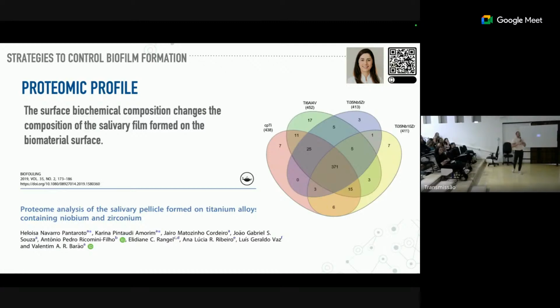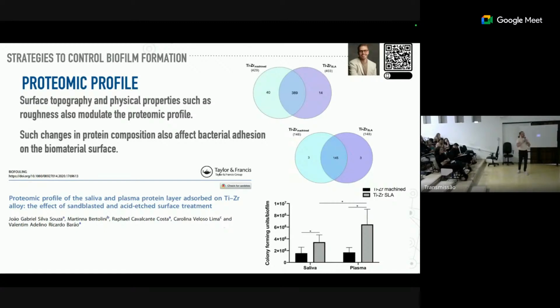We also checked for the same substrate. We're using only titanium, but compare commercially pure titanium, titanium aluminum vanadium, and also some experimental titanium alloys, titanium niobium zirconium. We also observed some difference in terms of protein absorption. Using the same material, titanium zirconium, for example, only changing the surface profile, only changing the surface composition. Here we use machined, and here we use SLA surface from Straumann.